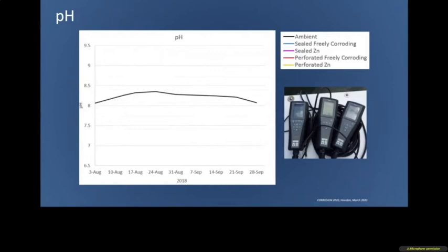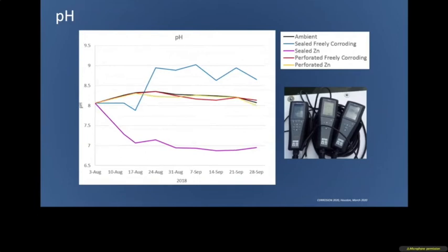But what about pH? One of the beauties of seawater is that it has a slightly alkaline pH. And one of the concerns is obviously ocean acidification, but that's a whole other topic. If we look at the sealed freely corroding pipe, we actually get an increase in pH. If we look at the sealed cathodically protected pipe, we get a decrease in pH. If we look at the perforated freely corroding and the perforated cathodically protected pipes, the pH basically stays pretty constant.